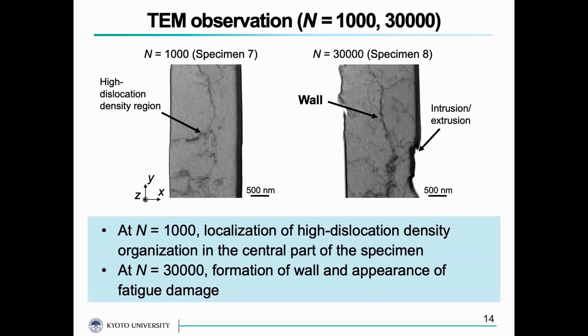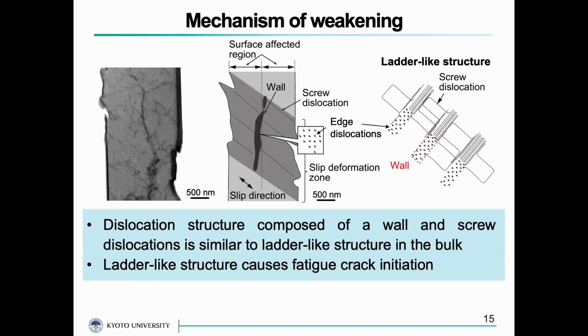At following cycles, the high dislocation density region localized in the central part of the specimen, and finally, a dislocation wall parallel to the longitudinal direction of the specimen was formed in the central part of the specimen. And fatigue damage like intrusion and extrusion was formed. The dislocation structure finally formed in micro-sized nickel single crystal was composed of a dislocation wall made of edge dislocations and screw dislocations in the low dislocation density region near the surface. And this structure is similar to the ladder-like structure in the bulk.